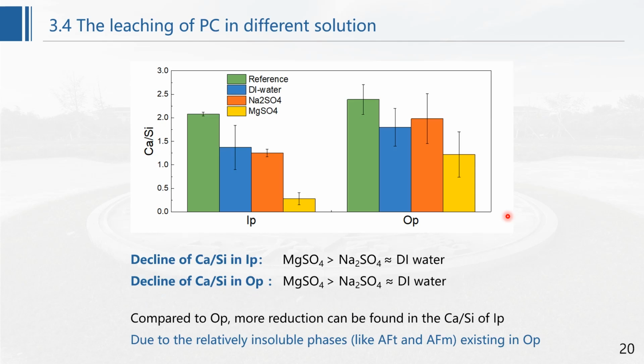Here is the change of calcium to silica ratio of inner product and outer product after leaching in different solutions. Similar to the results of unhydrated particles, the decline of calcium to silica ratio in magnesium sulfate solution is also the highest. Compared to outer product, more reduction of calcium to silica ratio can be found in inner product, which should be attributed to the existence of ettringite in outer product, which is relatively insoluble.